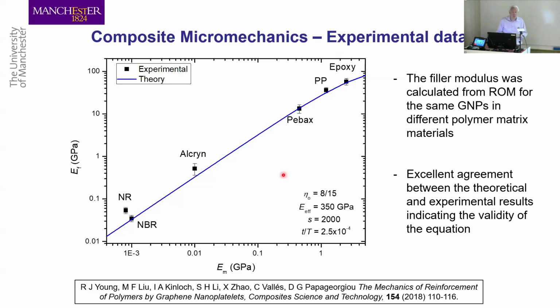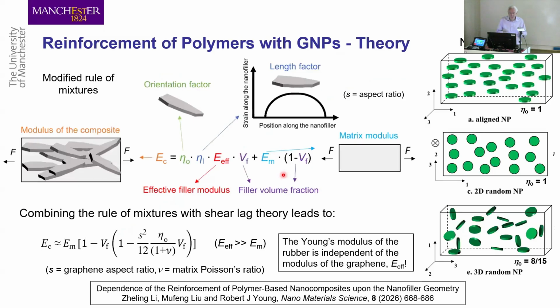It also tells us that most 2D materials will work in a similar way. So you can look at reinforcement with graphene nanoplatelets. We can go through all the mechanics of everything. Another factor is orientation, and we can factor in orientation. For 2D materials, orientation doesn't have such a big effect as fiber orientation. So we can work out the effective modulus of the composite, and we end up with a final equation where the modulus of the composite depends on the modulus of the matrix and the aspect ratio of the particles, but it's independent of the modulus of the graphene. So the stiffness of the graphene doesn't affect things.